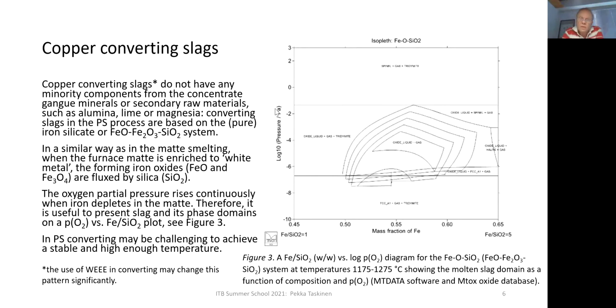to higher oxygen partial pressures of the crude copper. The unit here is Pascal. It's not atmosphere, and that is why these numbers may look odd, but typically 1 Pascal is about 10 to minus 5 atmospheres. So this is this top here, which is at 1275 degrees C.